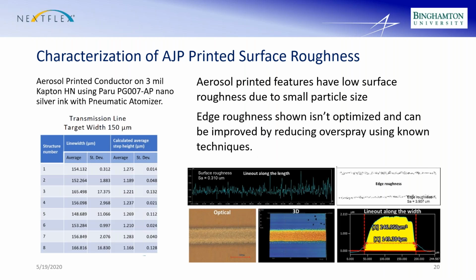All right, so as an introduction, we did some work on characterizing the aerosol jet print on the Optomec system, and we used a pretty standard ink, a nano silver ink on Kapton, and we just printed these transmission lines. In this case, we were measuring the surface roughness and the edge roughness, because when you print with an aerosol jet, you're just not going to get that nice, clean, sharp, etched copper foil type of stuff that you're used to. And that's one of the reasons why we're using a hybrid approach, because we can very easily and cheaply get a full circuit board of etched copper that would be very difficult to reproduce with aerosol jet, and frankly it would be probably more expensive. So we're doing the bulk of the printed wire and board construction using conventional means.